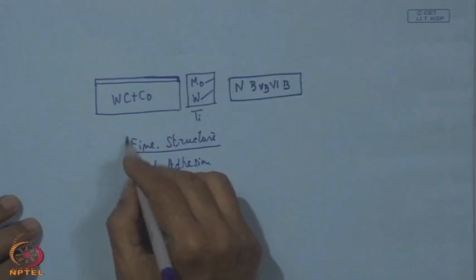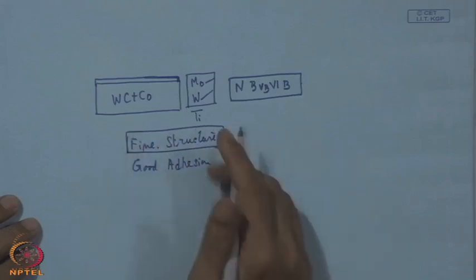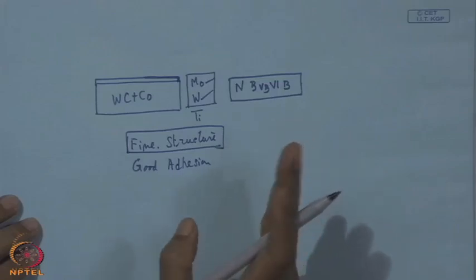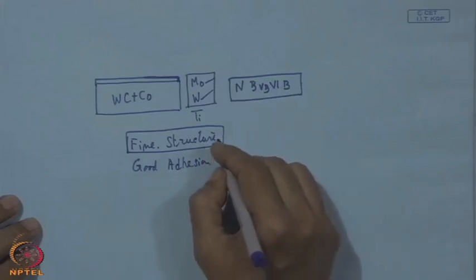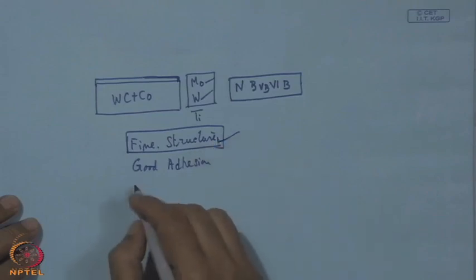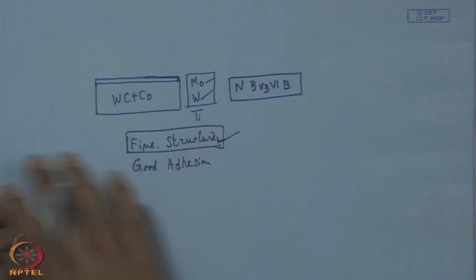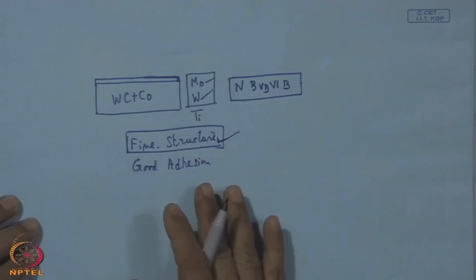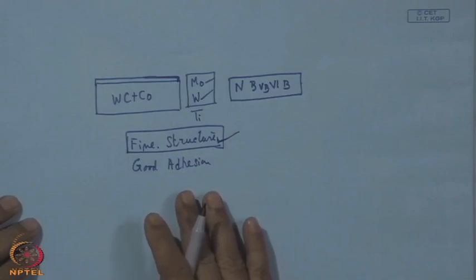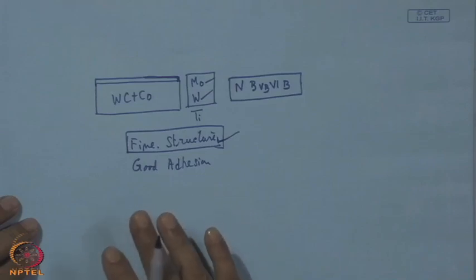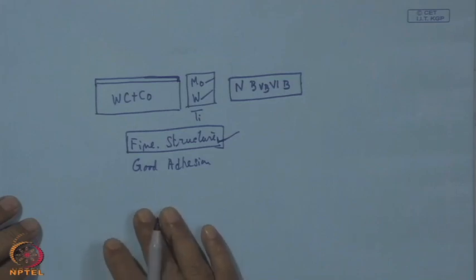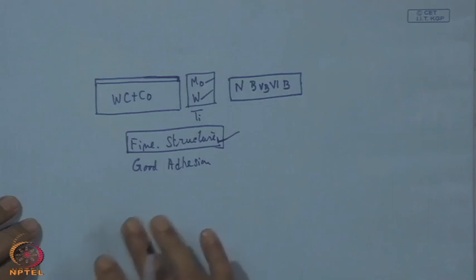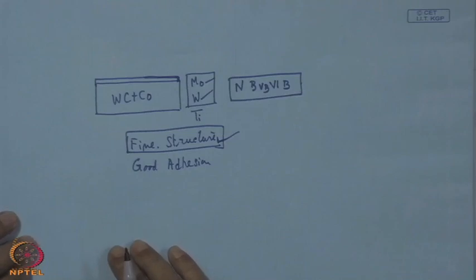So, fine structure is important if we like to use it for finishing operations. That means the working surface of the tool or the coating must have a smooth surface, smoothness. And the third one is that the coating process is capable enough to deposit on a complex geometry with uniformity of thickness and uniformity of property. These are the three basic requirements. They must be met in order for this coating to become a successful coated surface for machining application.